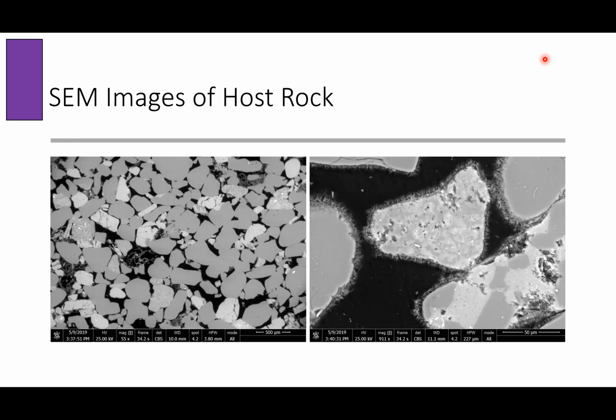That's a very good question. In this material, they were isotropic. We didn't have any anisotropy. We had a sample experiment that I didn't show where we tried, because typically for anisotropic material like shale, and we've studied shale and organic shale, we take the sample and we look at different orientations and we do scratch tests, and you see a difference. In this case, we didn't have any difference. And even when we looked under the optical microscope, we had a similar picture as what I'm showing of just the grains together. So for this sample, we didn't see any anisotropy.